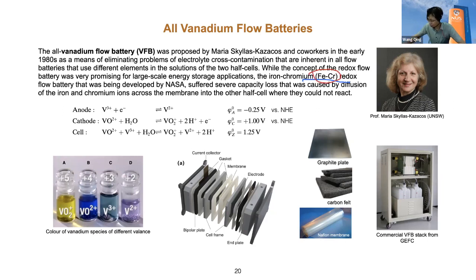like this iron-chromium one. So one side has iron 2+ and 3+, and the other side has chromium 2+ and 3+. These two pairs of redox species are dissolved in the catholyte and anolyte. And across the membrane, these ionic species can get mixed. And once they get mixed, that's a kind of self-discharge, right? And once they get mixed, it becomes very difficult to separate. So it becomes a critical issue for this kind of flow battery.